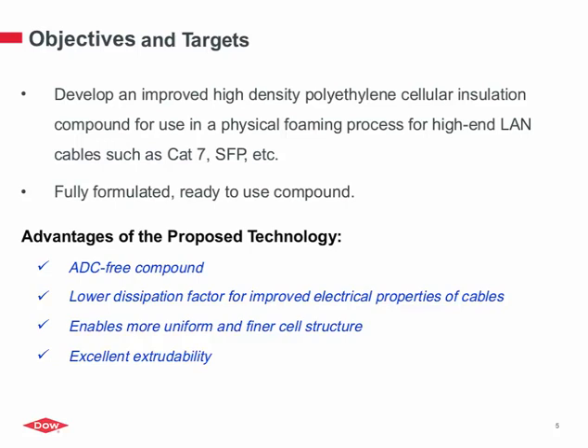So obviously the industry would like to have a REACH compliant system that would not have this problem. The second is that we would like to have a lower dissipation factor compared to an incumbent high density system for improved electrical properties of the cable itself. Obviously, as I mentioned, this uniformity and the fine cell structure is needed. And because of the speed that these lines run, there needs to be a compound that has to process with very good processability. So this line speed imposes some rheological constraints to deliver the processing speed.